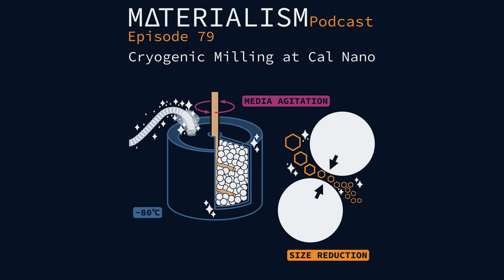I mean, we talked to a number of people in industry where there are a number of regulations actually on energy use that are coming down, especially for some of our EU guests. And if you can lower your temperature, that's 100 degrees lower temperature is a big deal. Yeah. So that's where the combination of, specifically for us, cryo milling with SPS, which also has in some cases a 90% reduction in energy compared to your traditional furnace sintering, that really makes this technology, with all these things with green technology and energy efficiency, right in line with that.